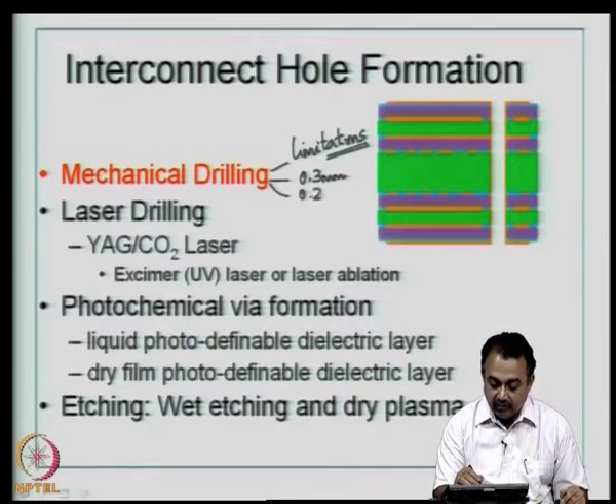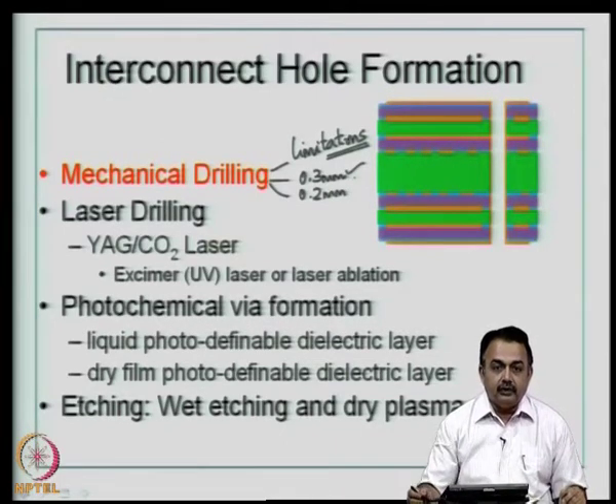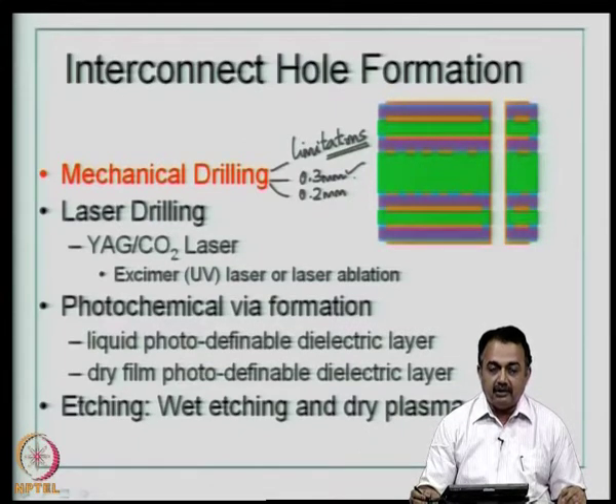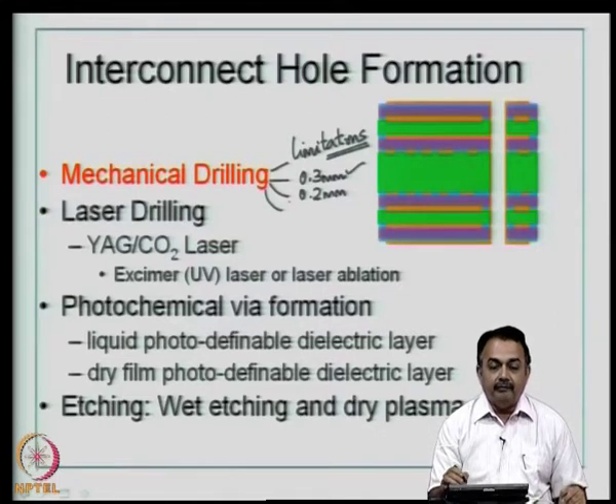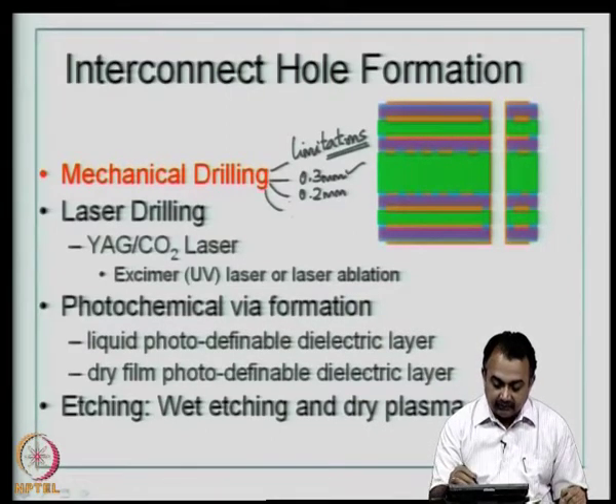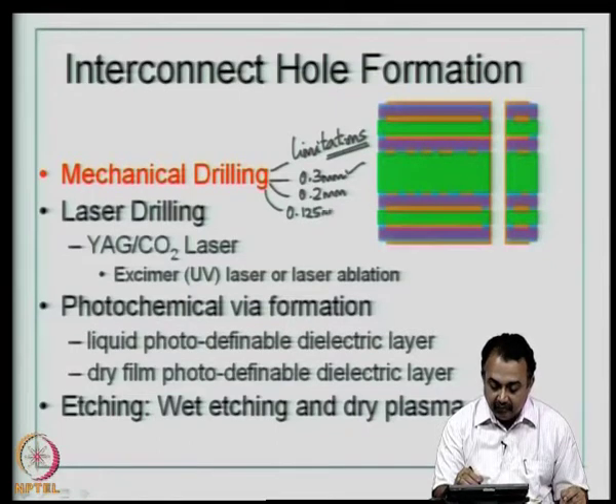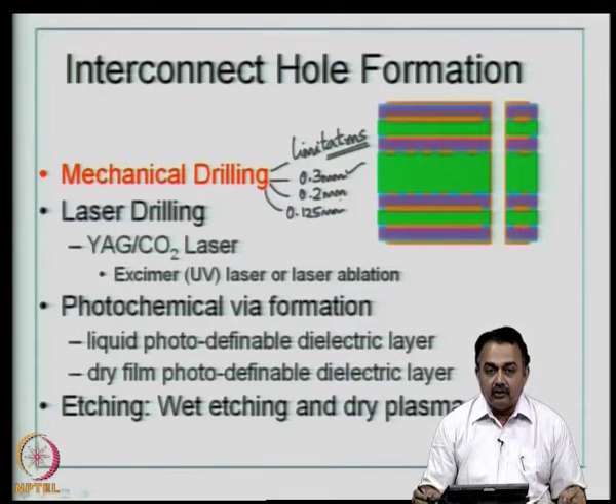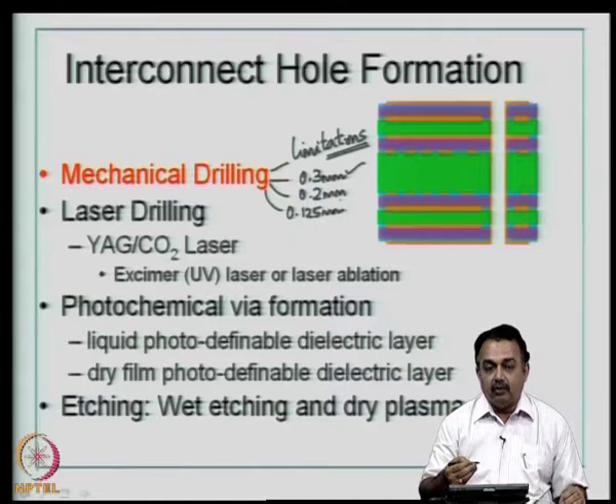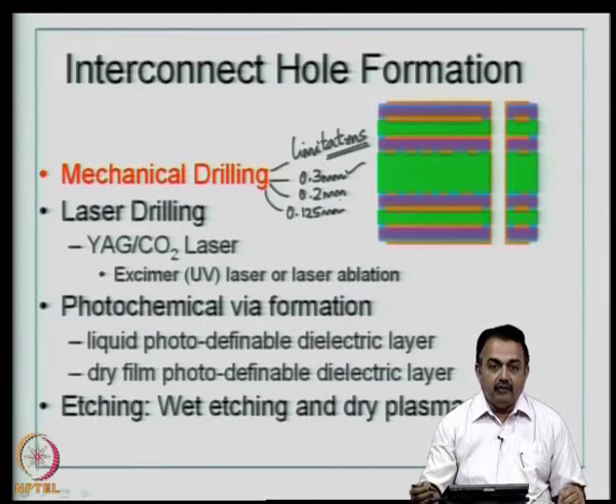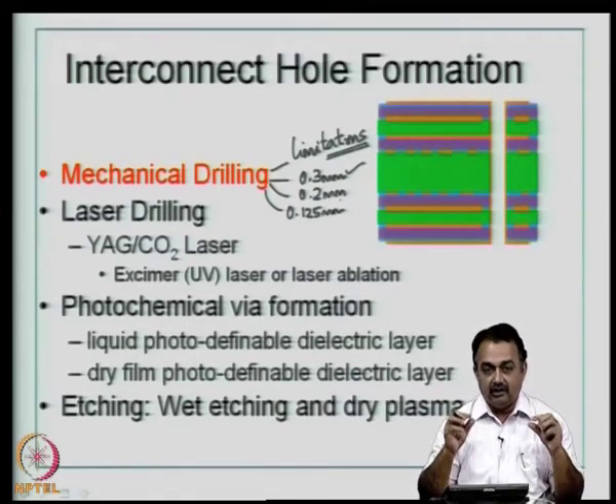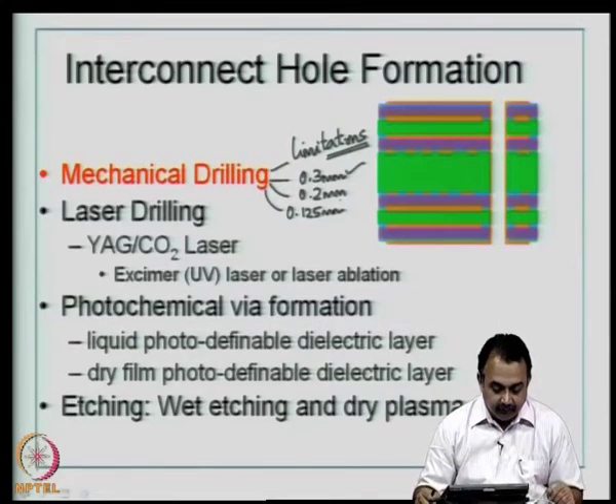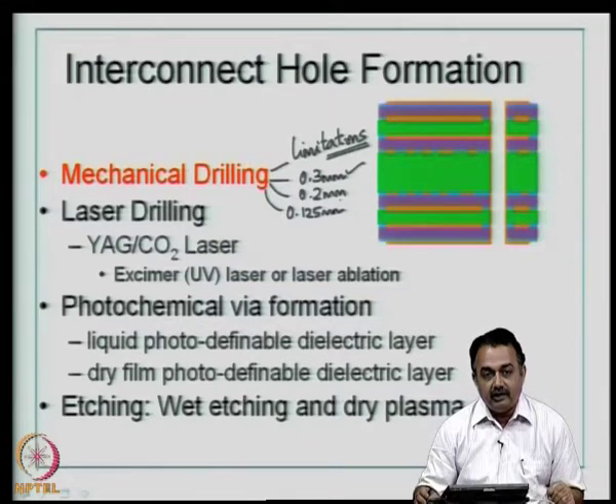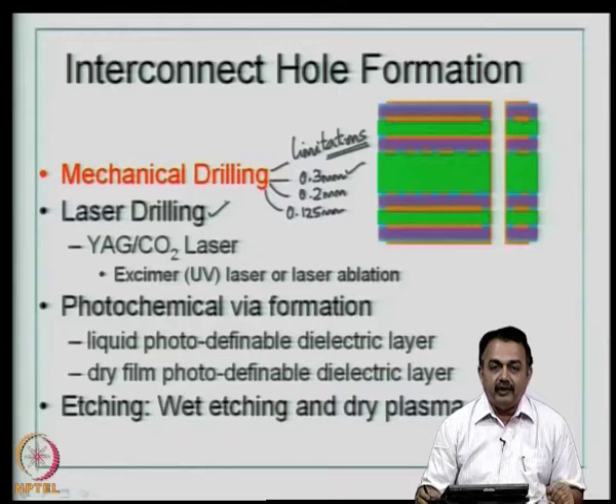but below that, let us say if you want to do 0.2 mm, 200 microns, it is expensive because the drill bit is expensive. The equipment also becomes expensive because of the high RPM that you have to use for lower drill bit sizes. But today we have mechanical drill equipments that can drill up to 0.125 mm, 125 microns. So, lot of quality control needs to be there, especially if you want to plate a through hole which is having a high depth. When you are using lower drill sizes, you have to make sure that the thickness is small, so that you can maintain the aspect ratio. The other options today that is available for building high density interconnects is to use laser drilling and do away with mechanical drilling.